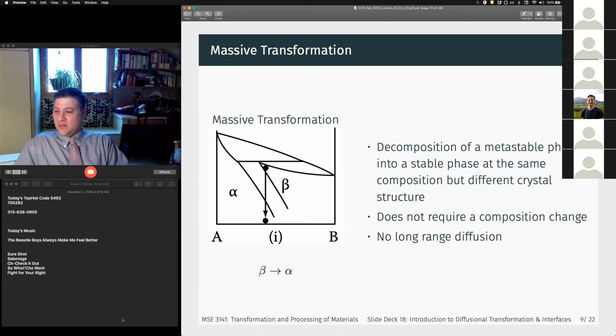When you say this does not require long-range diffusion, does that mean long-range diffusion makes this impossible, or it just isn't needed here? And here, for a massive transformation, it's not, right? Because we're keeping the composition the same, right? We're going from beta of this composition to alpha of the same composition. So we don't need to move any solute over long distances, right? All we need to do is some local atomic rearrangement, right? So that's what I mean by long-range diffusion.